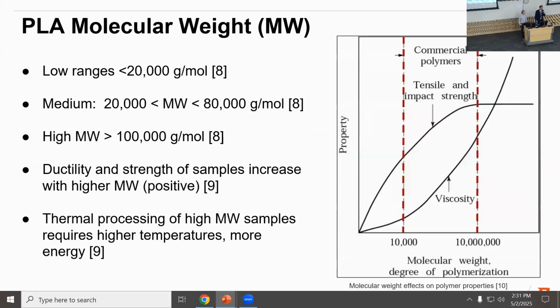It also has a very large range of molecular weight, with lower weight samples being below 20,000 grams per mole and higher ones well exceeding 100,000 grams per mole. This means there's a wide range of temperatures that can be worked with and a large range of mechanical properties. The higher the molecular weight, the stronger it usually is: the longer the polymer chains, the more bonds that need to be broken in order to be deformed or impacted. So that is a good thing, but unfortunately, it also means that it must be worked with at a higher temperature in order to properly get it into a molten state.